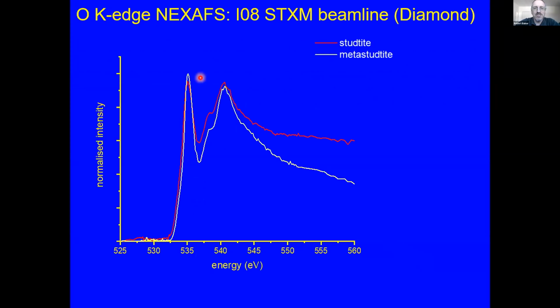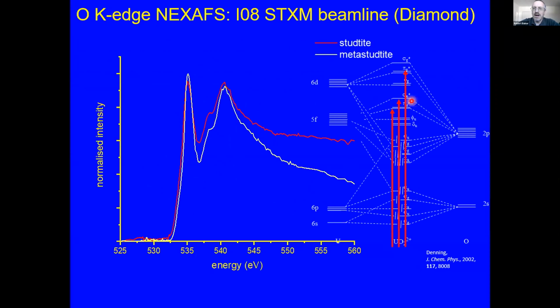And we did actually manage to measure some spectra. So this is the oxygen K-edge spectra of studtite and metastudtite. So if we look at our MO diagram now, we should expect to see 3 or 4 transitions, one to the pi star U, the sigma star U, and the pi star G. We should also see this guy here as well, but nobody in the literature has really ever seen it before.